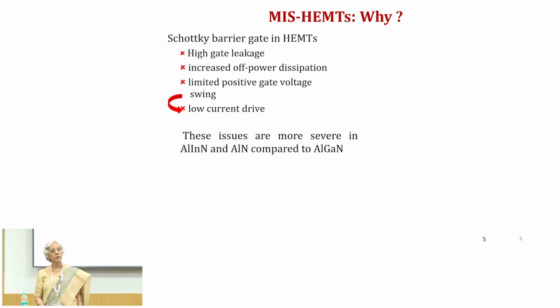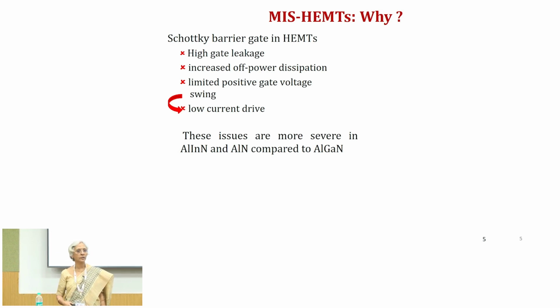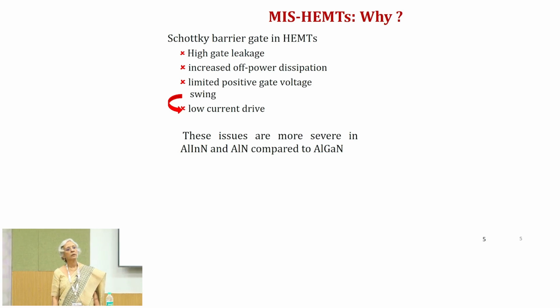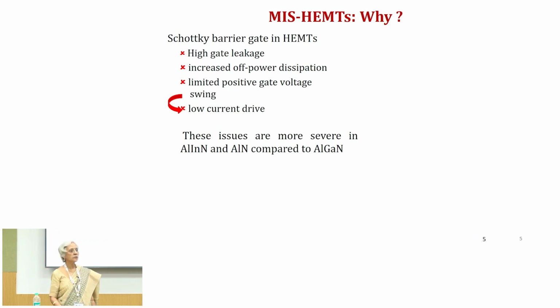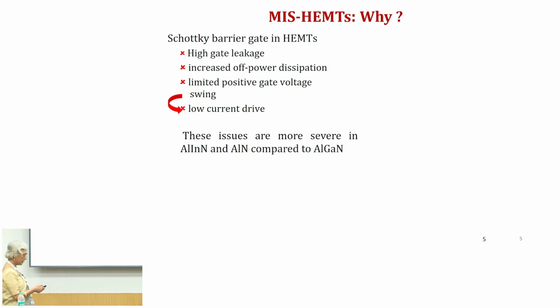Now, because this electric field is much higher, on one hand it is good because it allows us to go for a thinner barrier layer, and therefore, we can have high transconductance. But the other problem is that because this electric field is so high, the gate leakage is also very high, because mostly the gate leakage mechanisms in a Schottky gate depend on the electric field, whether we are talking about Poole-Frenkel or Fowler-Nordheim tunneling. Because this electric field is so high, you will see that in the aluminum indium nitride gallium nitride heterojunction we get high leakage.